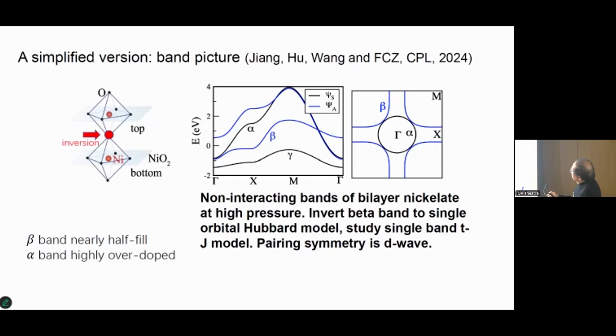So the simple band will give us this four-band. If you solve this problem, you have this beta band and alpha band, like the blue ones. And this alpha band is similar to what I mentioned, the red ones, which is almost free. The blue ones in the calculation actually show the combination of the two orbitals. But let's forget about this orbital, we found this band.